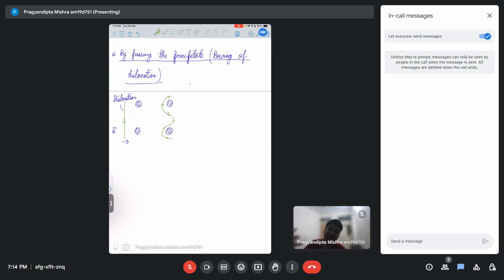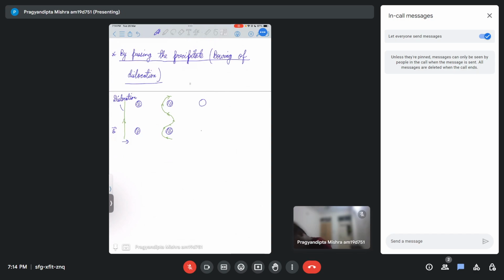Now as the dislocation keeps going, it will keep going around the precipitate. Okay, it is not able to shear the precipitate. It has to keep going. So in the next step, what will happen is, now the two ends of the bow will reach very close to each other. Okay. So essentially, you will see something like this. Okay, they're very close to each other.